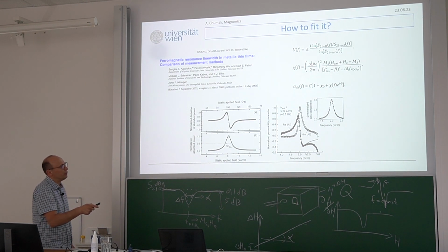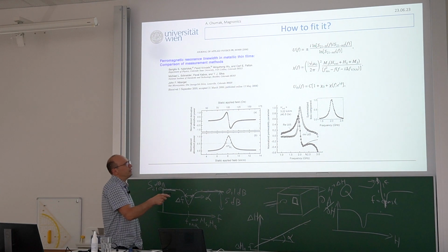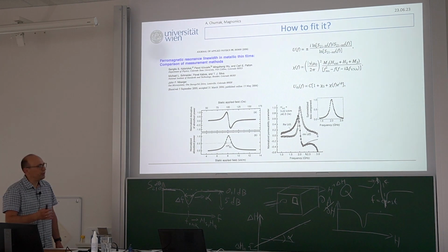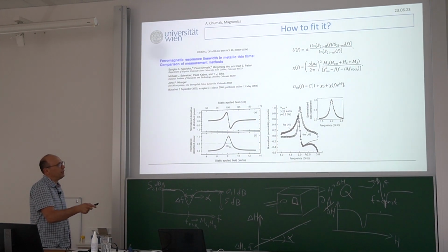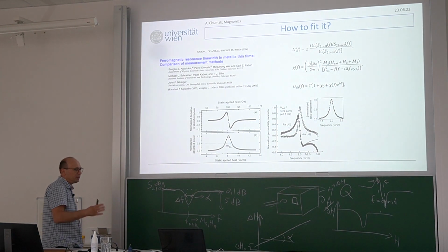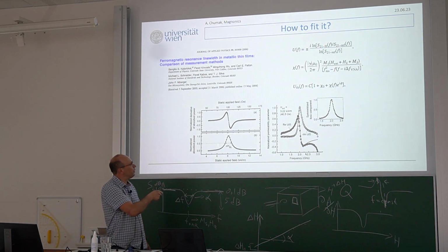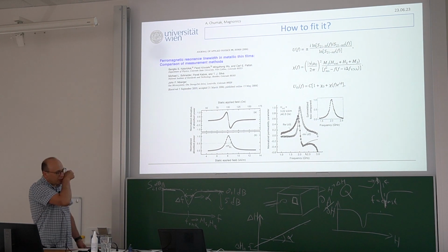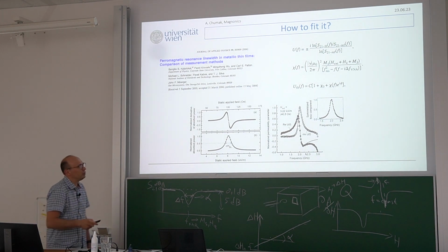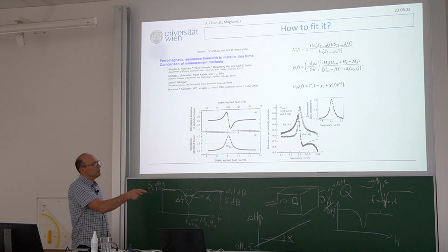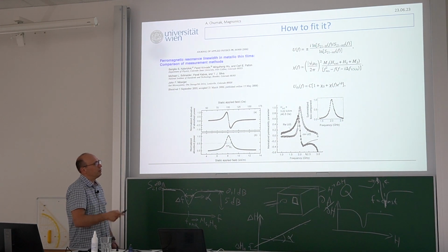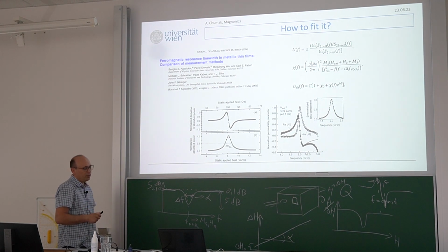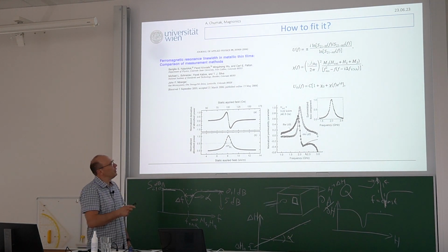But what's important here in practice is this phase e^(iφ), because it gives you the opportunity to switch from a symmetric to an asymmetric profile. Sometimes when you perform measurements, you see that your curve looks a bit more symmetric, or sometimes you start getting such asymmetric behavior, depending on which material you use and so on. Therefore this phi is critical, and it often helps a lot to fit using this function. Therefore, I just recommend you to try this approach.